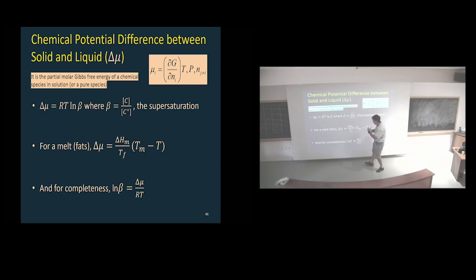Now, in a melt, it's different, even though they're the same thing. So you have the enthalpy of melting that you determine from a DSC, the temperature of melting, and our famous delta T. And of course, you can combine one with the other one. This is very easy for us to get because everybody in the fat industry has a calorimeter, and with that you can get these two parameters.